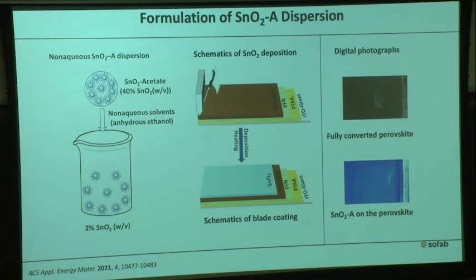After that, we tried to find the stability of this tin oxide solution in different perovskite-compatible solvents. This tin oxide likes lower alcohols, and we can make a very stable solution up to butanol. It also likes other polar solvents, but here we are more interested in lower alcohol since that is perovskite-compatible.